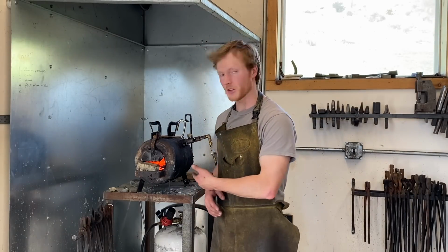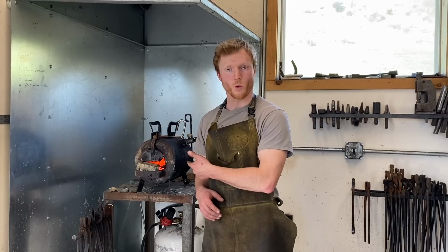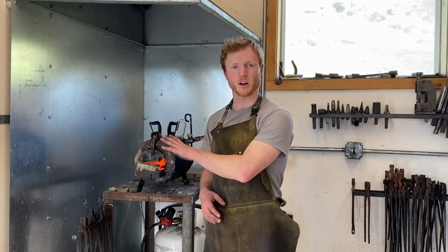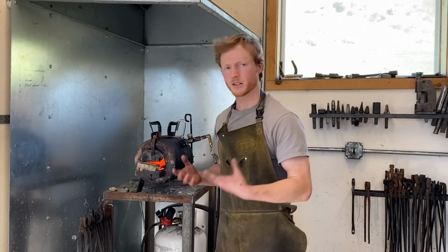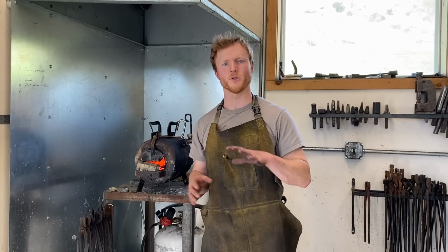Anyhow, I've got the piece warming up in the forge. I've just shut off the forge after forging it, so it's heating up to maybe 1600 degrees, and then I'll let it air cool. And that'll kind of normalize it, reduce some of the tension in the steel, and if I need to make any little adjustments, I can do that cold with the hammer. And that's hopefully going to be a lot easier than trying to see where the bends are and that sort of thing when it's hot.